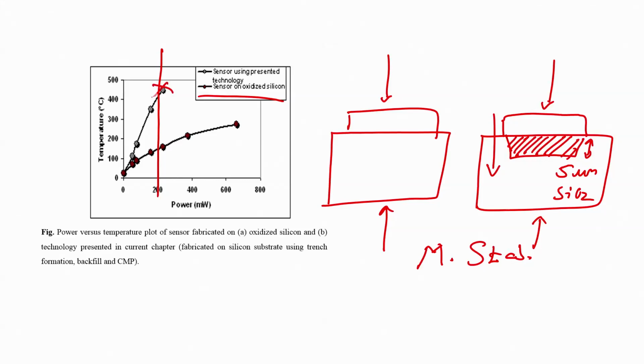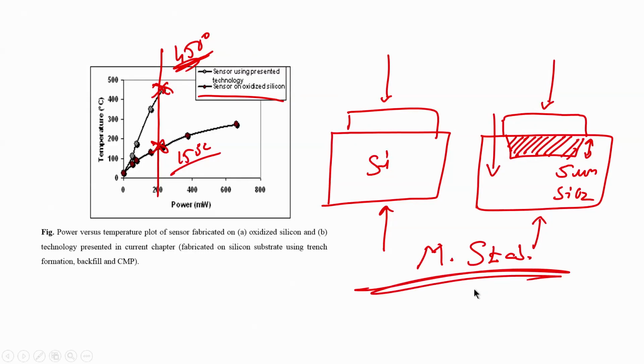If this is my 450 and this one is 150, I have a difference of 300 degree centigrade at the same power when I compare with the silicon substrate and sensor fabricated on silicon substrate, and my mechanical strength is almost similar,